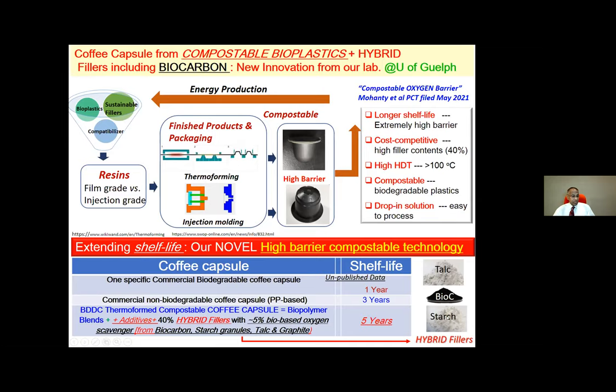So compostable plastic and the hybrid filler with biocarbon, talc, and starch. This is a biofiller, this is a biofiller, and this is a mineral filler. So those are the fillers we use, around 40% or more. So we use two types of processing, whether it's injection molding or thermoforming. So accordingly, we engineer our total formulation by melt flow control. And these are quite sustainable fillers, bioplastic blends, and compatibilizer. That is what the innovation is. Here is an extended shelf life, our novel high barrier compostable technology. It's unpublished data, but a patent has already been filed.